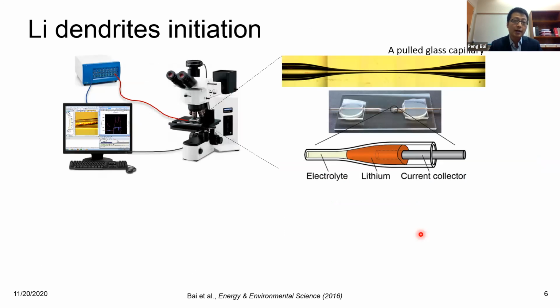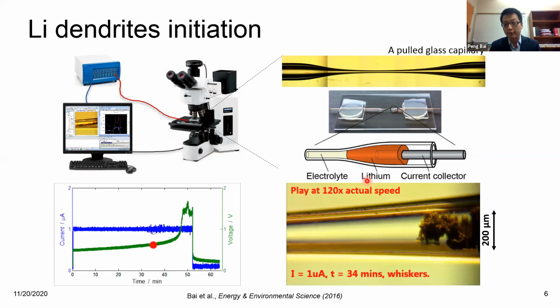So one interesting question: how did this dendrite form? Several years ago, when I was a postdoc, I invented this capillary cell. You can see here, we use just an optical microscope to observe the dynamic process. Here, the difference is that we use a glass capillary, heat it in the middle part and pull it further so that we get a very, very thin channel here. And we can push in lithium metal to form the lithium symmetrical cell. The convenience here is that we will be able to see the entire electrode within the field of view, so you won't lose any details.